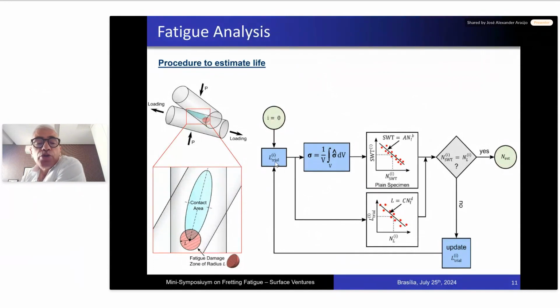Simultaneously, as we need to guess the L at the beginning, this L corresponds also to a life in the LN curve. If the life estimated in the SWT here is equal to the life of the LN relationship, then it means that we guessed the correct L size. If not, we keep doing, okay? When we get the life estimated by SWT equal to the LN, we have my estimated life for these components.